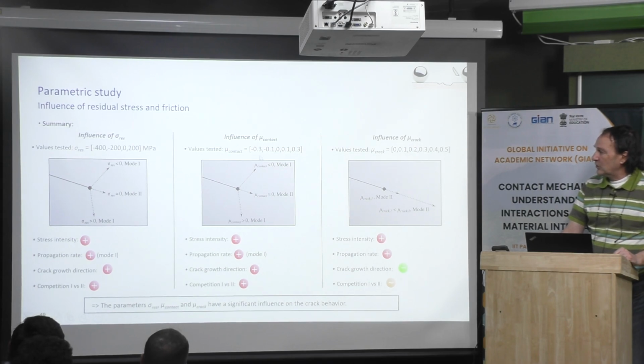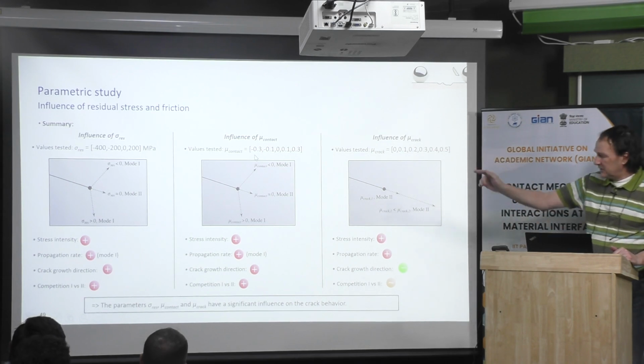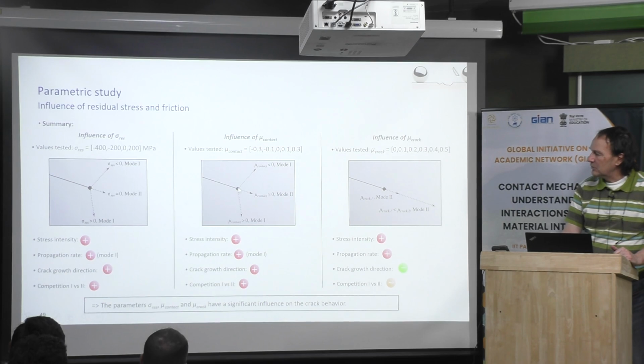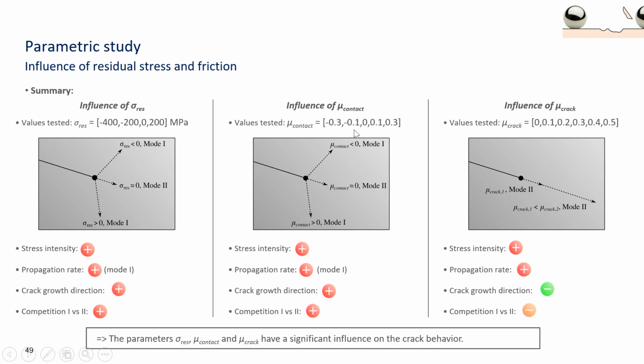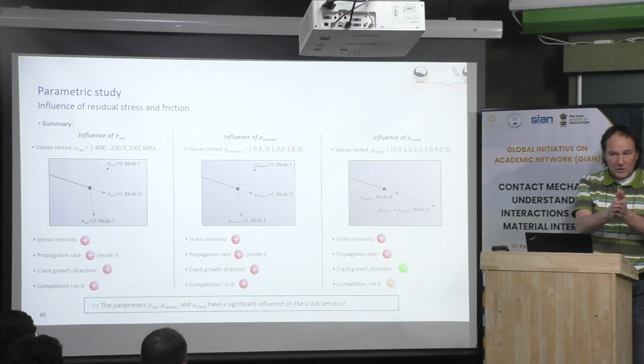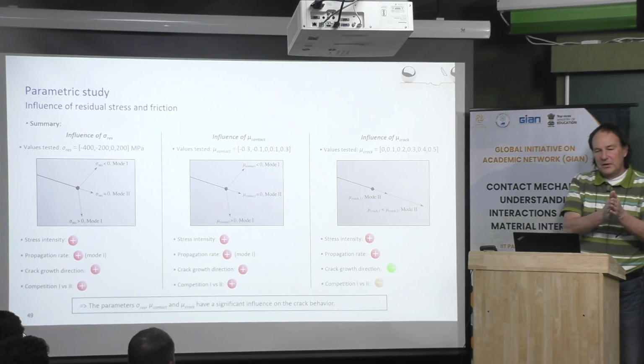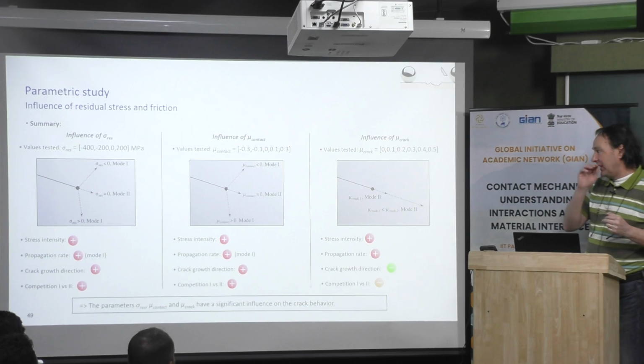Then there is the friction coefficient, and it depends on the direction of friction, of course. It can play a very important role in how the crack is branching. However, when it is lubricated, the friction coefficient is very low. It's typically a few percent. Then, even if mathematically it can have some effect, in reality this is not what we expect to see. And there is also the effect of the friction within the crack, of course. If you have a lot of friction, it will stop the crack propagation. But if you have no friction, typically in mode 2, in shear, you may accelerate the propagation.